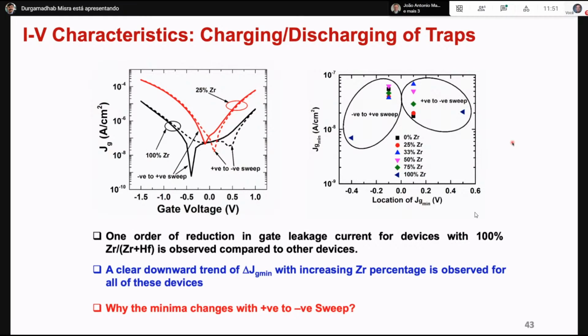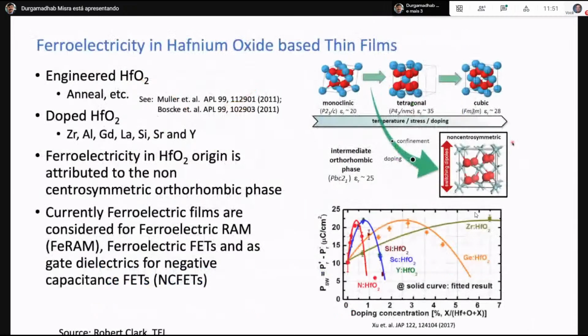Why this minima changes was actually the first question we asked. This was a few years ago, and then I discussed it with people in the research community. It turned out to be a very interesting result we found: the ferroelectricity in hafnium oxide. When you add zirconium, around 50% of zirconium, the ferroelectric properties develop. There is a polarization, and the origin is attributed to the orthorhombic phase. It changes to the orthorhombic phase.